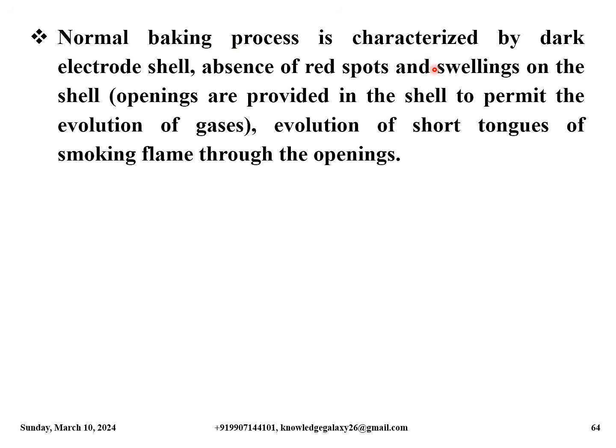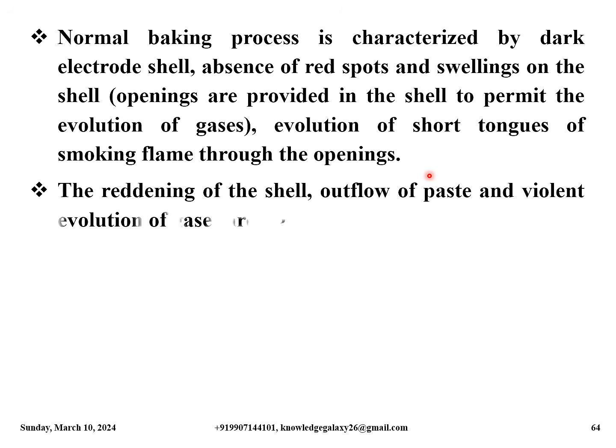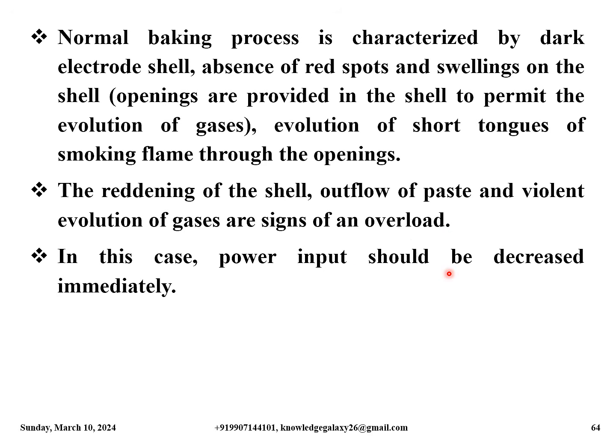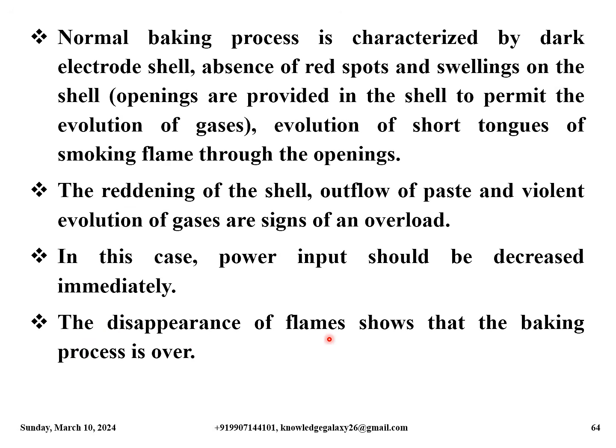Normal baking process is characterized by dark electrode shell, absence of red spots and swellings on the shell, that is, openings are provided in the shell to permit the evolution of gases, evolution of short tongues of smoking flame through the openings. The reddening of the shell, outflow of paste and violent evolution of gases are signs of an overload. In this case, power input should be decreased immediately. The disappearance of flames shows that the baking process is over.